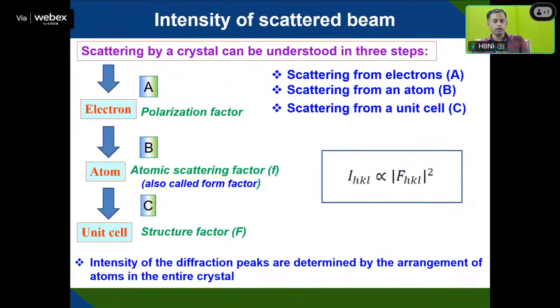So far, whatever we discussed, from the diffraction peak position and intensity, you will be able to identify what phase is formed. And from the peak profiling, the FWHM, you will be able to get the microstrain or the particle size, the crystallite size that is formed. Mostly the X-ray gives crystallite size.